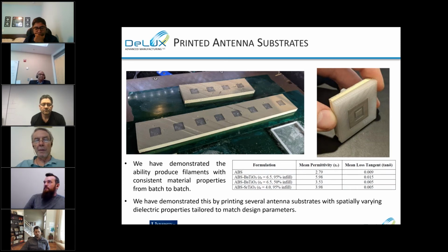So you can see this outer area is all a dielectric constant of 6.2. The inner area is a dielectric constant of 2.68, and then there's a top portion here that is a dielectric constant of 2. So to get all of those dielectric constants into one 3-dimensional substrate with printed conductors on the surfaces and embedded within, to do that without additive, you're going to have a ton of piece parts and a difficult time making that antenna substrate in general. We're able to get very low loss tangents with tailored dielectric filaments. Right here I'm showing a dielectric filament that has up to 5.98 with a loss tangent of 0.015.